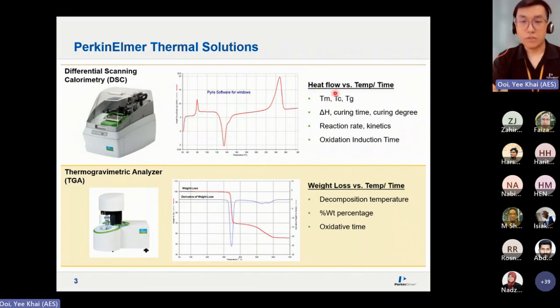Hence heat flow versus temperature or time. As I've mentioned, the reason you do have the time profile is because you are heating your sample under a controlled heating rate. So you get your melting temperature, crystallization temperature, glass transition temperature, depending on your sample nature. Now, again, thermal analysis is not a tool for you to do identifications. It's more like a characterization tool.